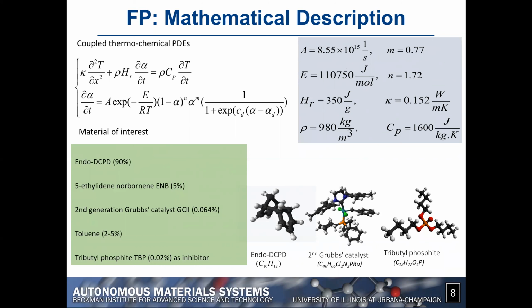One key contribution that we've made to this process is the introduction of phosphite as inhibitor. The idea here is to introduce a very small amount of phosphite that allows the monomer, or the catalyst, to remain inactive for a substantial amount of time, so we can actually manipulate the monomer before we really trigger the frontal polymerization. And you will see an example of that a little later.